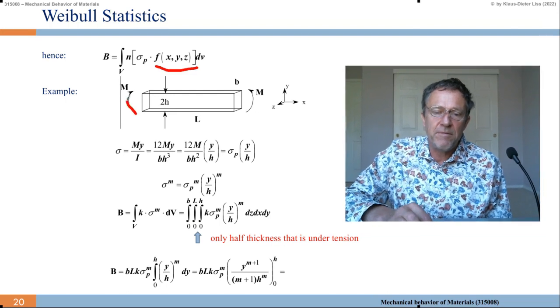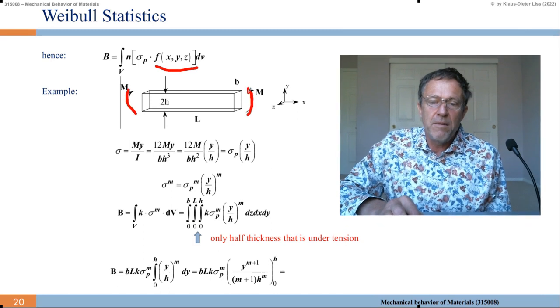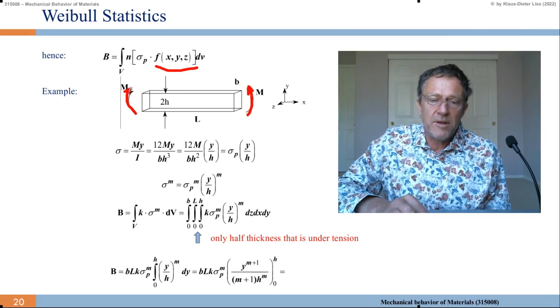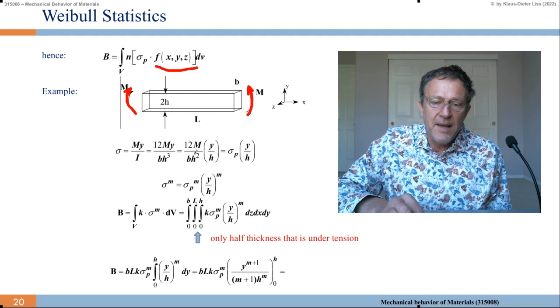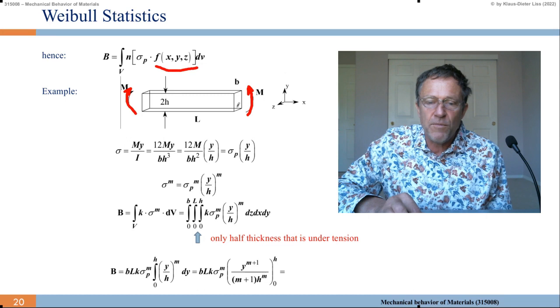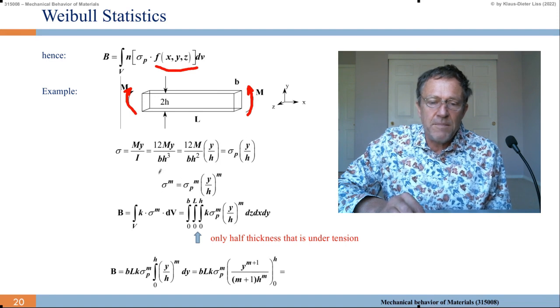For example, we have had the bent beam with two moment torques at the ends, otherwise free. So we can look up the sigma. We have done that in the theory of elasticity, and it works out sigma is sigma p y over h. We see here's the coordinate system, y is the vertical, and 2h is the height of that beam. So the stress is sigma p times y over h. And now sigma to the m equals sigma p to the m times y over h to the m.